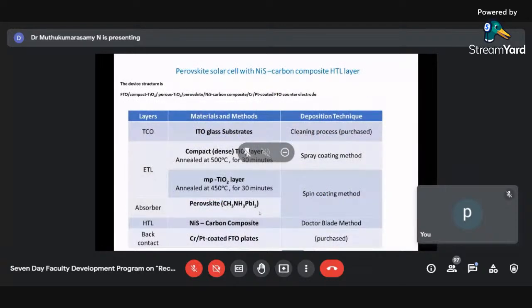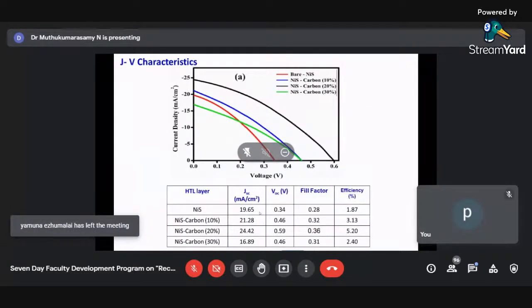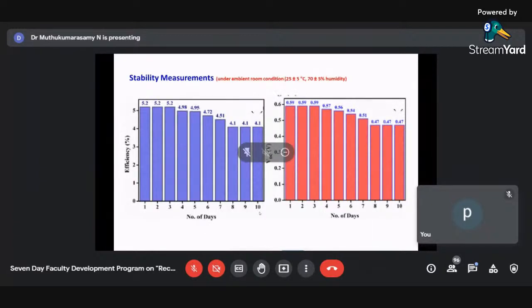So this was the methodology which we followed to fabricate a solar cell. We got a maximum efficiency of 5.2% with 20% carbon incorporated nickel sulfide hole transporting material. And we did the stability measurements, because whenever you work with perovskite solar cells, stability measurement you have to definitely do. That is very, very important.